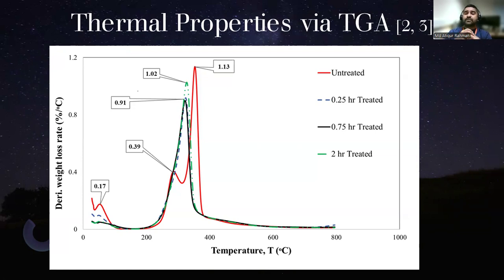Second peak, which is 0.39 at that peak. That peak is the representation of the hemicellulose, and the last one, the top one, is the representation of the cellulose. So for all the treated, there is no second distinct peak. From the TGA, we can confirm that the hemicellulose has been taken away. That's why for the treated fiber, there is no distinct second peak over there.